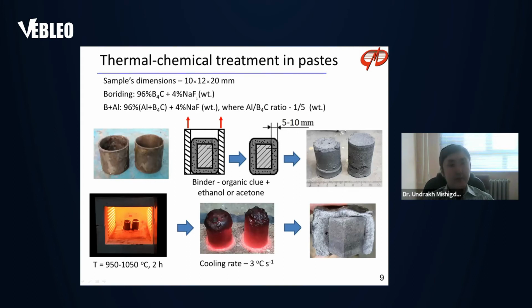Before treatment, samples were cut into rectangular pieces with these specific dimensions. Then, as boron and aluminum sources, boron carbide and aluminum powders were used respectively, and a small amount of sodium fluoride was used as an activator. And for boroaluminizing, the aluminum to boron carbide ratio was taken as 1/5.